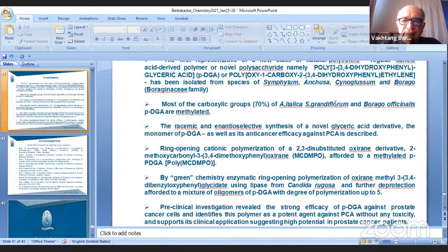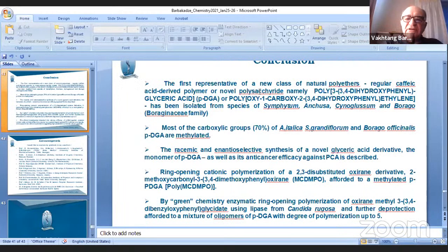So, conclusion. The first representative of a new class of natural polyethers, a regular caffeic acid-derived polymer, or novel polysaccharide, namely poly-3,4-dihydroxyphenyl glyceric acid, or polyoxy-1-carboxy-2-(3,4-dihydroxyphenyl)ethylene, has been isolated from species of Symphytum, Anchusa, Cynoglossum, and Borago, Boraginaceae family. Most of the carboxyl groups, 70% in Anchusa italica, Symphytum grandiflorum, and Borago officinalis, are methylated. The racemic and enantioselective synthesis of a novel glyceric acid derivative, the monomer of PDGA, as well as its anti-cancer efficacy against prostate cancer, is described.